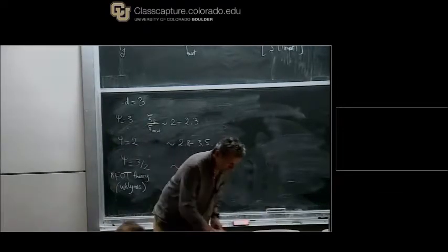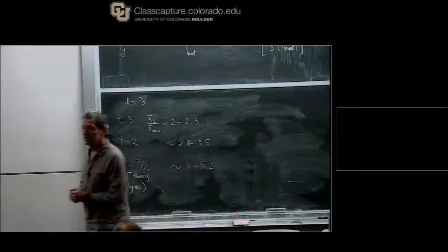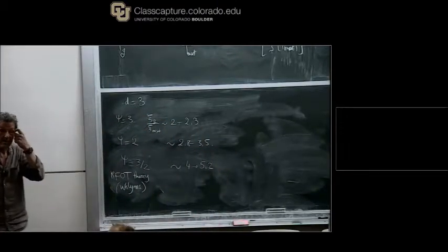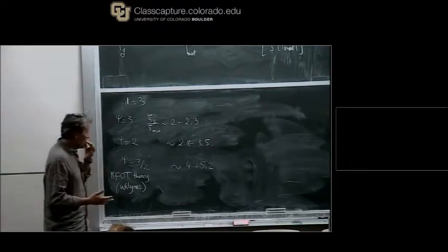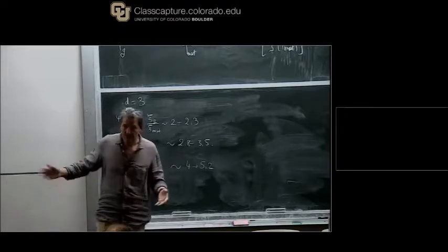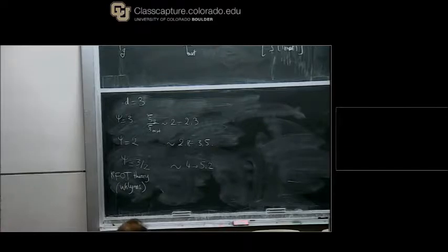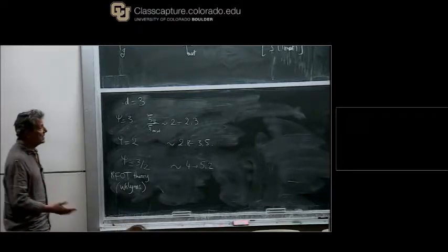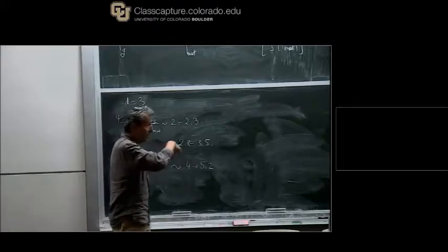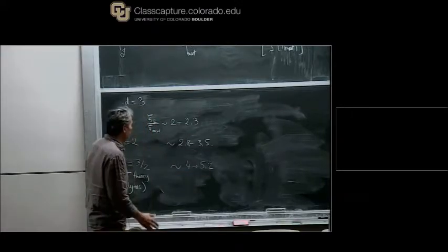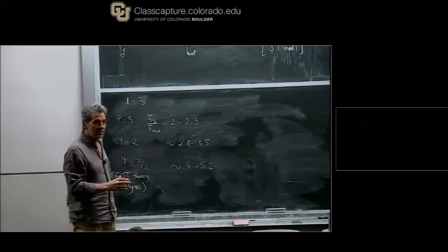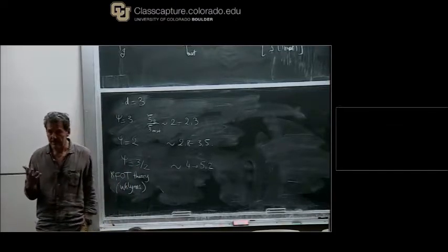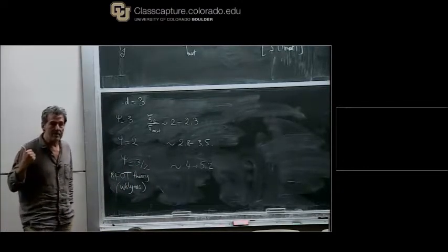So this is a crude estimate, but again, it's telling us something: if we have, as the empirical evidence seems to be, some sort of activated dynamic scaling that is also suggested by the upper bound, then you see that you don't need a big change of the static correlation length to explain the 16 orders of magnitude change of the relaxation time.